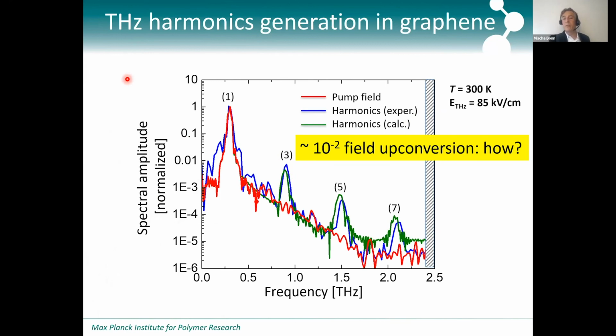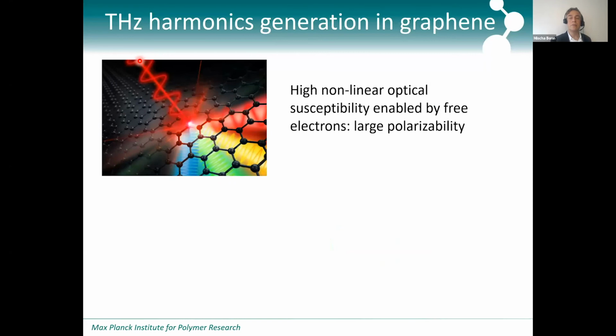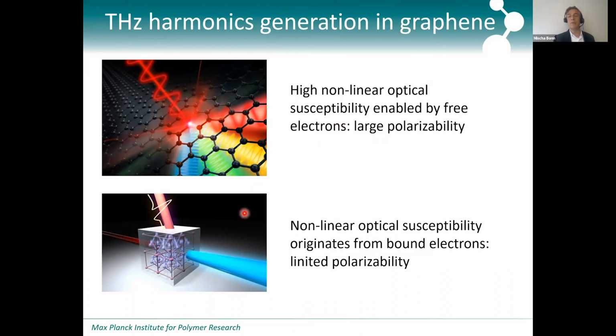So how is it possible that we have this incredibly large third order nonlinear susceptibility, or this effective susceptibility with this material? The reason for that is actually very simple. What we make use of is the extremely large polarizability of the free electron. So we're literally driving the free electrons over mesoscopic, hundreds of nanometers length scale through the material, and thereby we create a huge polarizability, which, if you look at a normal, say, BBO crystal, where you do second harmonic generation, what you use there is the polarizability of bound electrons and not free electrons.